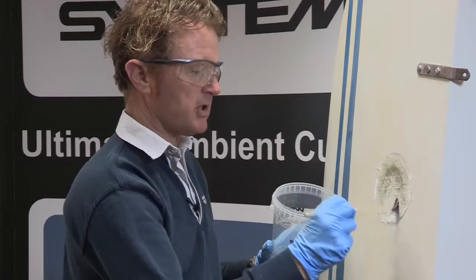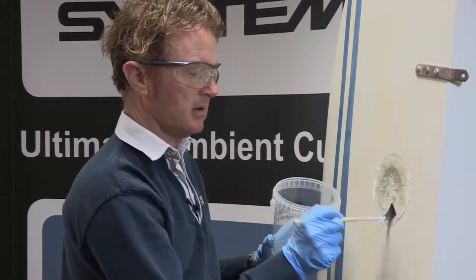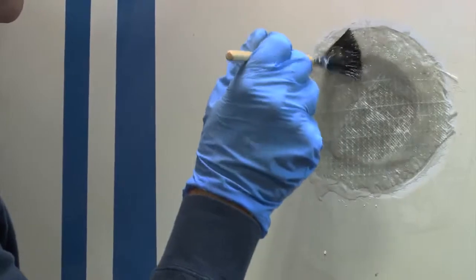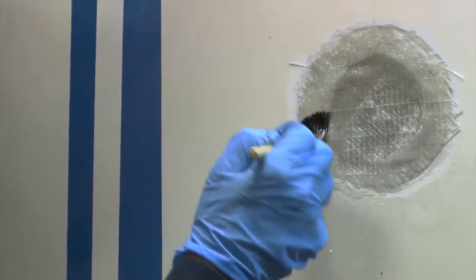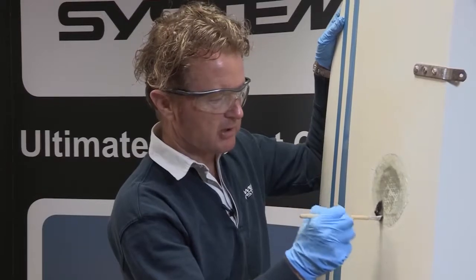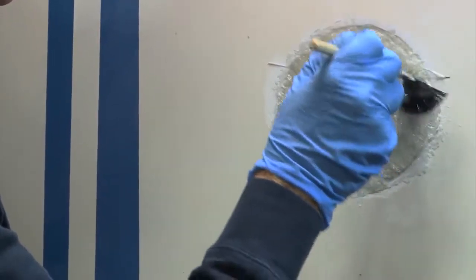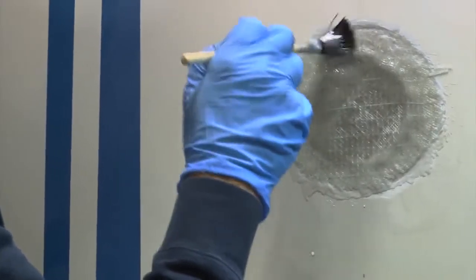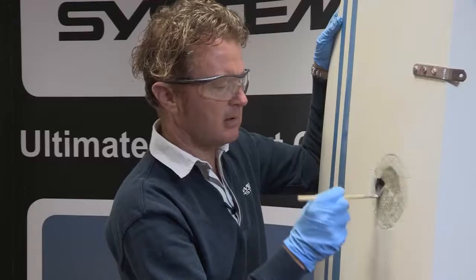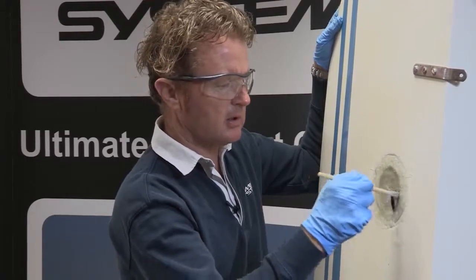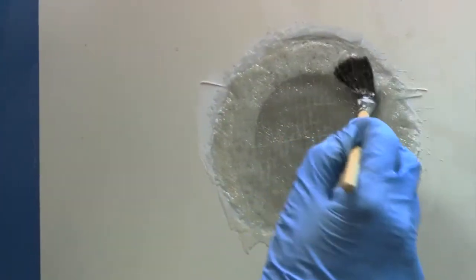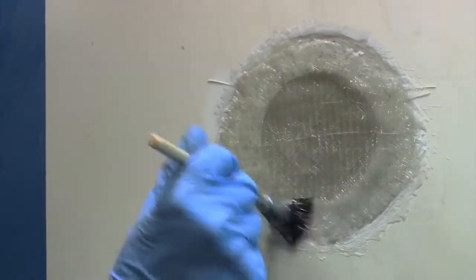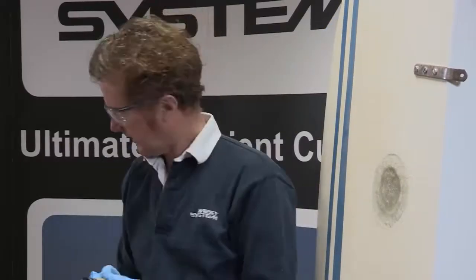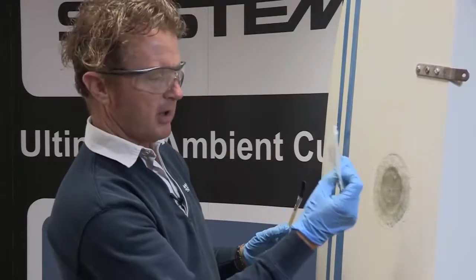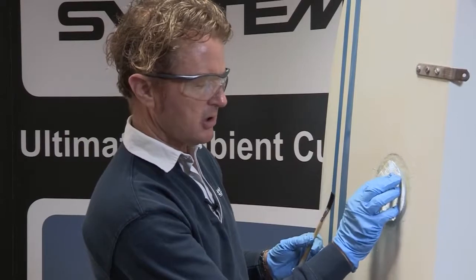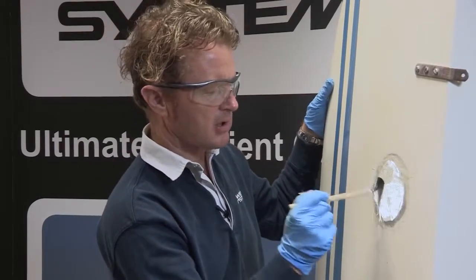You can see this absorbs the resin hardener mix very, very quickly. It's worth spending some time on each layer, really consolidating the glass fabric just by stippling the surface, really using a degree of force to compact the glass and make the repair very, very dense. I'm just working out all the air bubbles. It looks a little bit resin rich, but then our next layer will absorb a lot of that excess resin. I'm going to line the fibre up with the stitching so it's all in the same orientation, then apply the next disc.